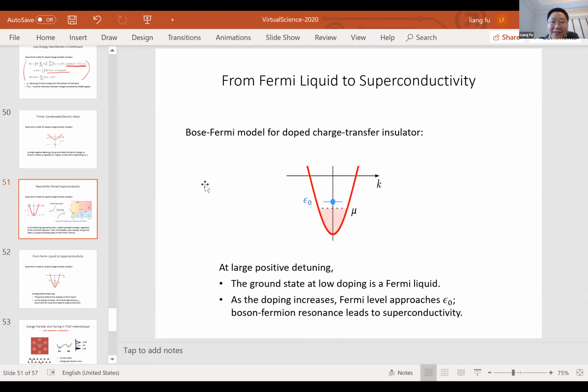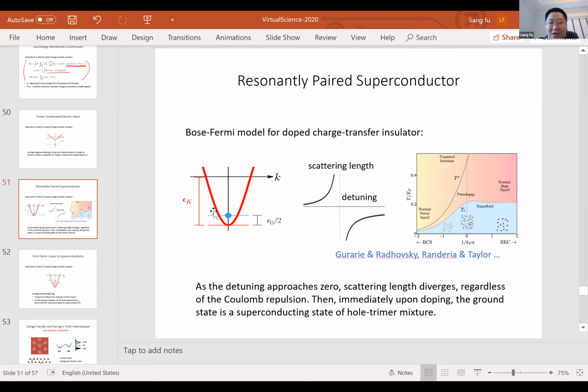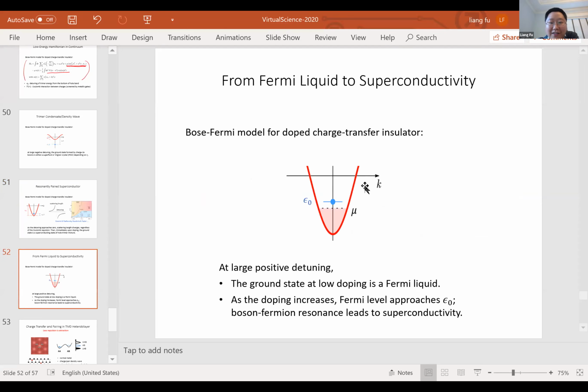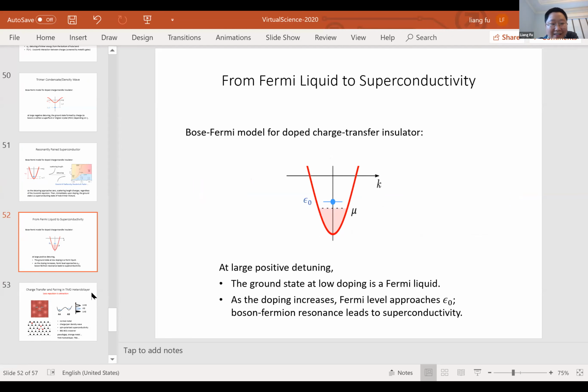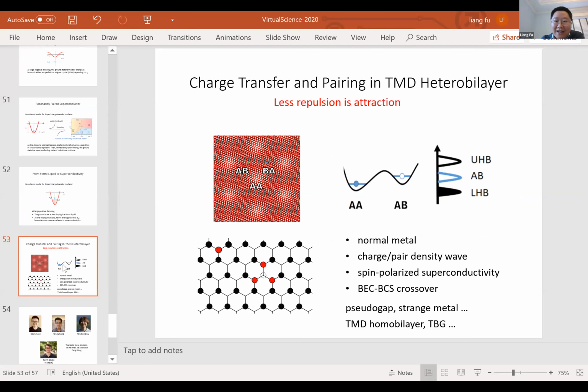So the difference is that if the system is tuned close to resonance, when the trimer energy is close to the bottom of the hole band, then immediately upon doping, the system changes from a charge transfer insulator to a superconducting state. While in this second scenario, when the detuning is positive, the system starts as a Fermi liquid upon doping, and only above a critical doping does it become superconducting. So this is essentially everything. Let me summarize it here.